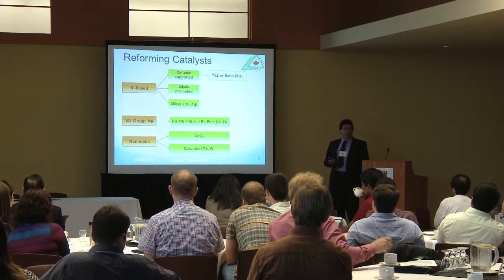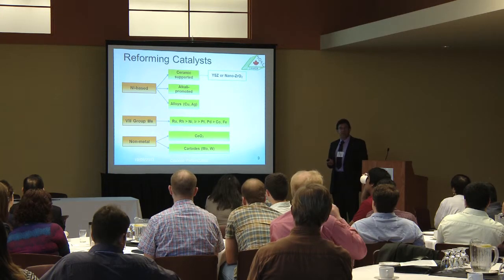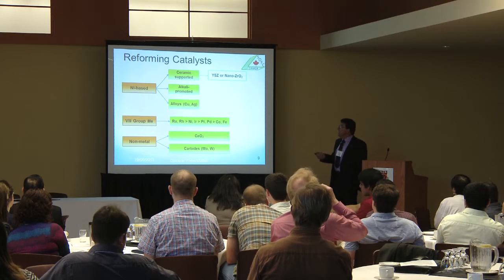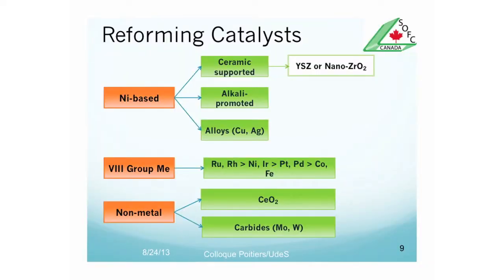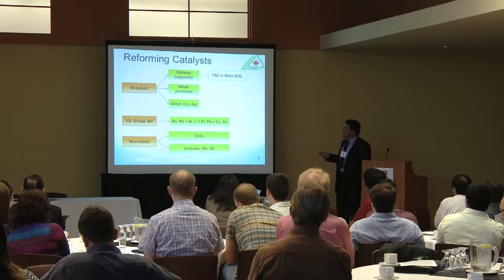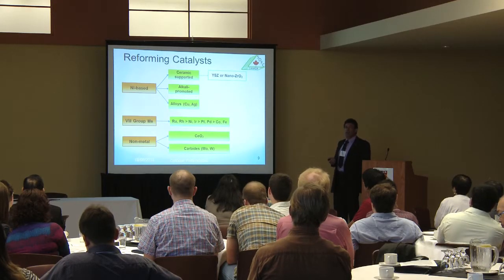Alkali promoters were used and are commercially available for decreasing the amount of carbon. However, the alkalis at high temperature devolatilize and the catalyst loses its activity, but at the same time we have deposition of alkalis in other places of the system. And the alloys which have been used have lower efficiency.